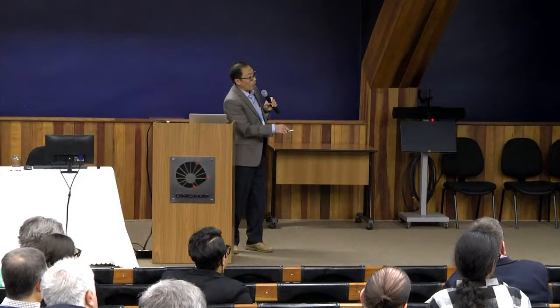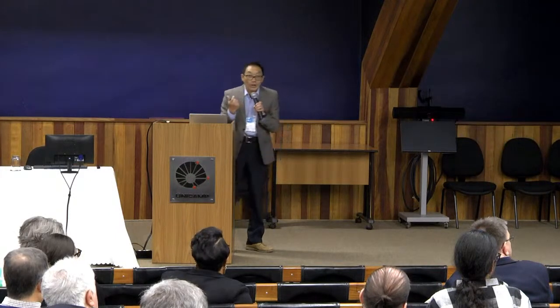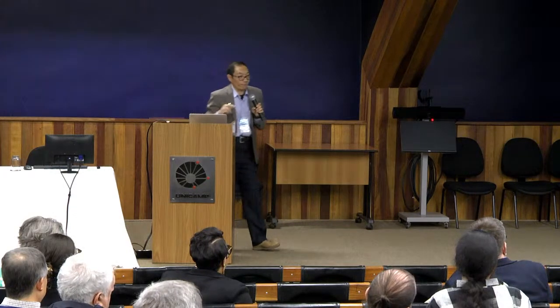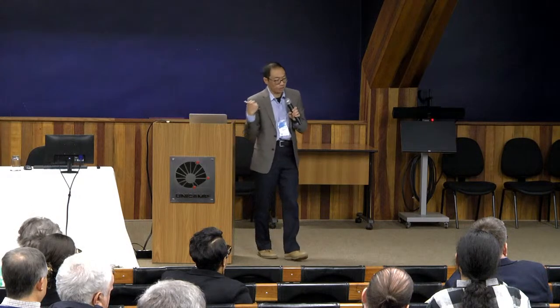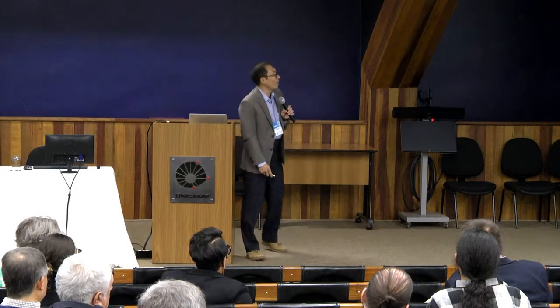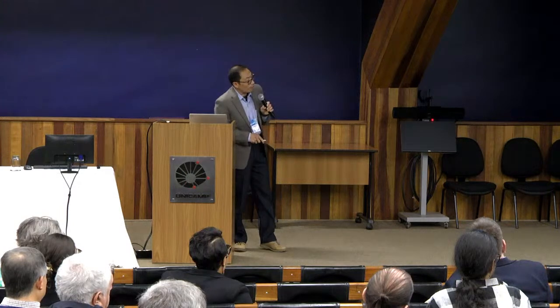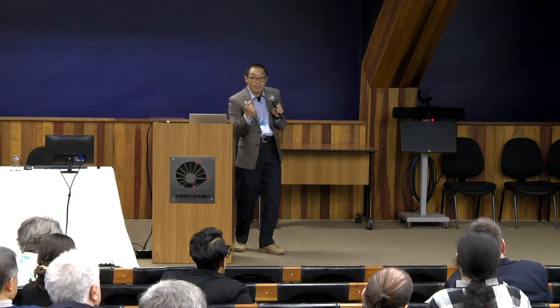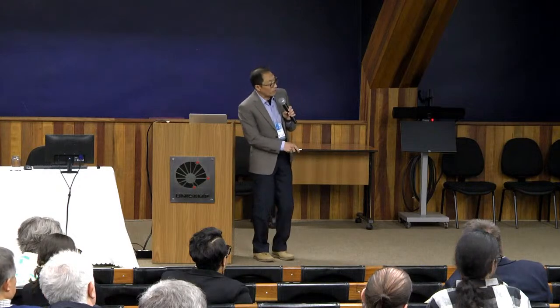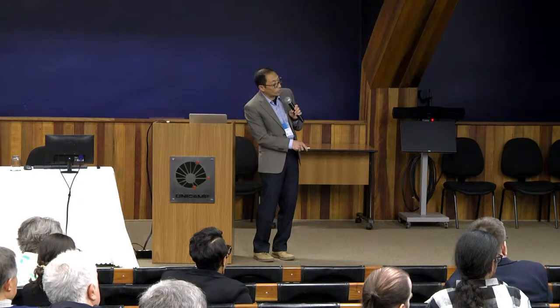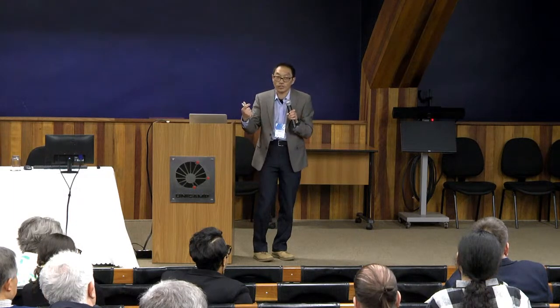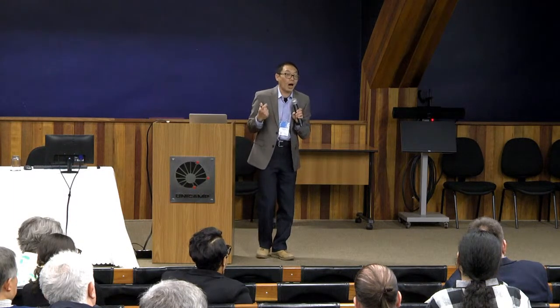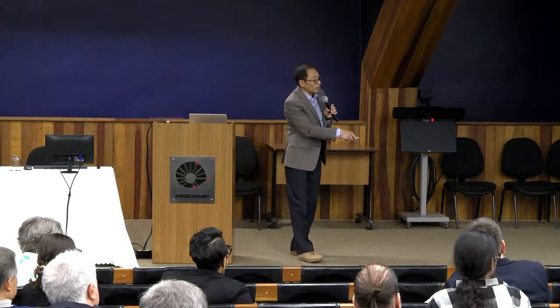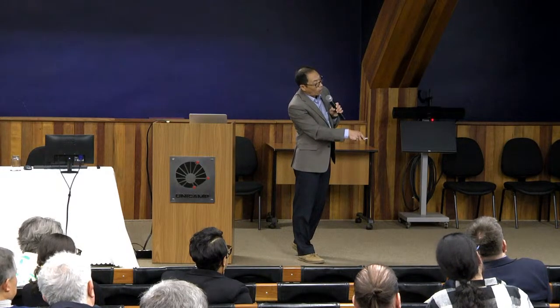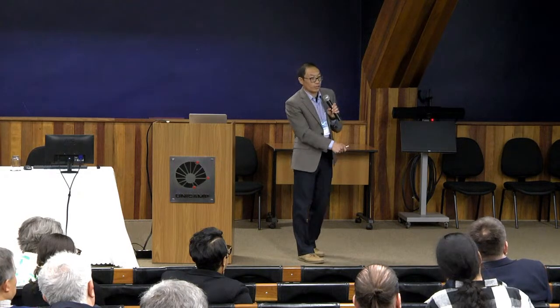And the majority of what you can see by RIXS in the oxidization and reduction of the oxygen, however, is fairly reversible. But I will come back to this topic again. It's still not good enough. So when we compare this with another material, which I said has limited oxygen release, what we see is the capacity itself is much better because we don't have the oxygen release. The reversibility of the oxygen redox is much better. So the fade out of the capacity compared with this is a lot better.